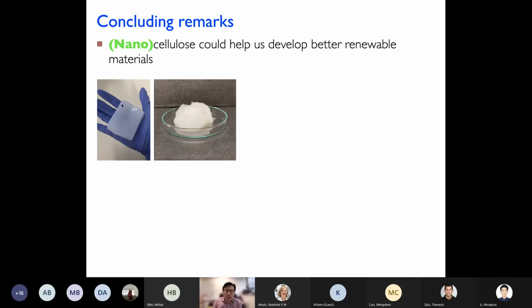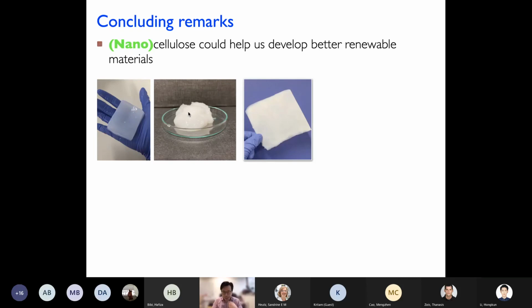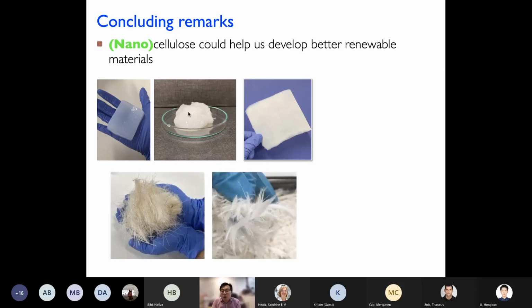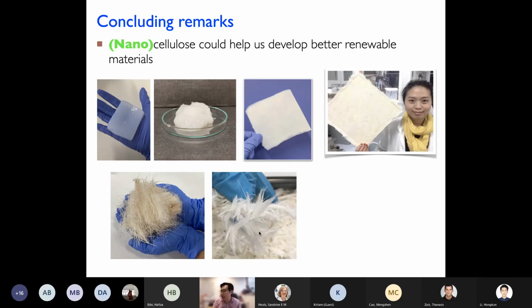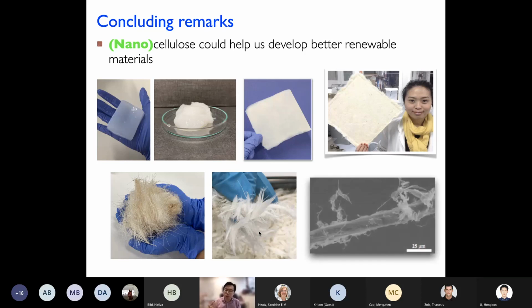And the problem with cellulose, or nanocellulose, is that it's actually extremely hydrophilic. So one way to get around this hydration problem is to make nanopapers out of it. You had seen a couple of examples there where nanopaper can be impregnated with a resin to produce nanopaper reinforced polymer composites, or you can use these nanocellulose to bind these loose fibers, feathers together, producing a rigid fiber preform there. And in many cases, we don't need to go down to the isolated nanofibers in this particular respect.